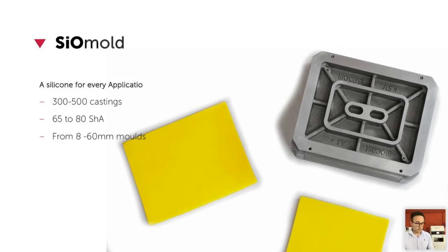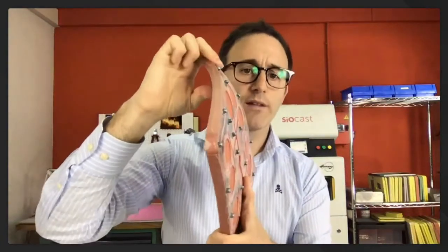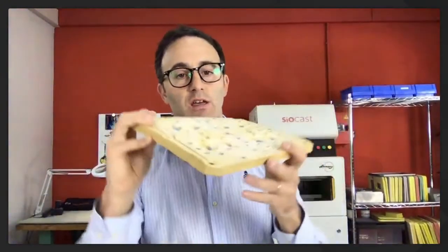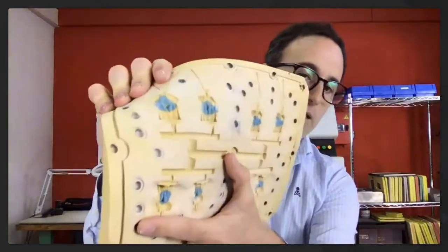And we also can supply different types of silicones. Here, I will show you the differences from the mold that you were seeing before, of the coins. This mold is 80 Shore A flexibility. It's quite stiff, and this is suitable for flat parts or parts that don't have heavy undercuts. This silicone is 65 Shore A. It's a much more flexible silicone. That means that you can cast much more complex parts that you will be able to remove from the mold more easily. Also, we can supply other types of silicones, you will see in the video in the next presentation, that are able to prevent detaching or tearing of the silicone in very complex areas. Okay.